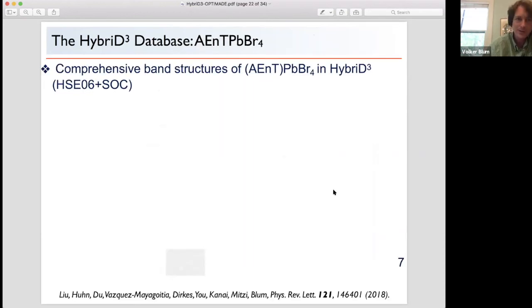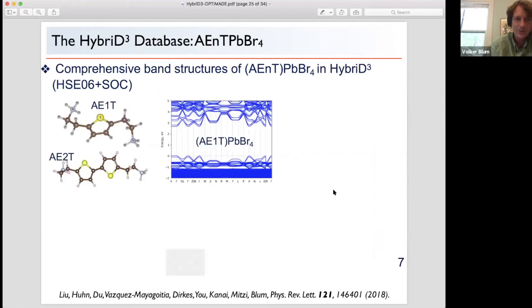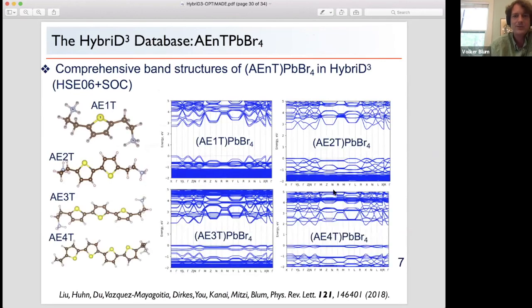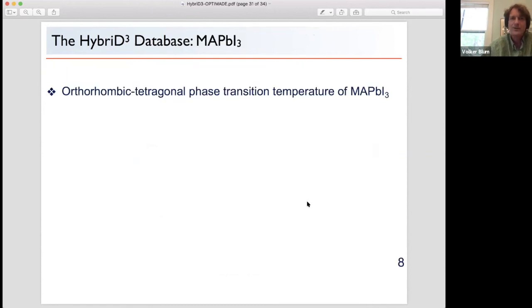Very good. You can do this for more materials. Let's see, what have we here? For materials where you just theoretically, so this material actually doesn't exist experimentally. You just theoretically put in a molecule based on plausible positions from X-ray diffraction and look at the evolution of band structures. And so we did this because this was actually the starting point for us to research these things, to find out if we could systematically predict trends in some agreement with experiment, and it turns out we can. And so we have this data in here. Of course, we try to get more. Then there's the purely experimental data.